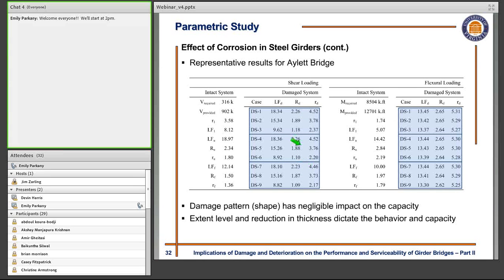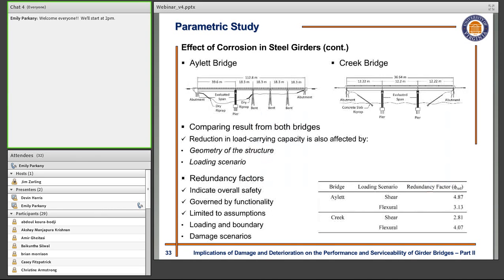So we can argue here that the shape of the damage or corrosion does not have major impact on the capacity of the system, but it is the extent level and reduction in the thickness that may dictate the behavior and capacity of these types of in-service structures. We performed the same type of analysis for other structures, the Creek Bridge, and we realized that in addition to the loading scenario and also the damage cases, the geometry of the structure itself may have significant impact on the level of safety that a structure can provide under the different simulated damage conditions.